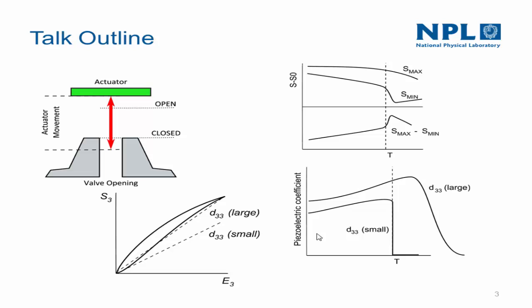Okay, so first of all, I said earlier about, for example, an actuator for opening and closing a valve. Then for these actuator applications, we're looking at large fields generally, and we're also interested in thermal expansion. So these large fields, the effective D33, or the strain that you can achieve at a particular value of electric field, may or may not bear any resemblance to a small field D33 measured, for instance, using resonance.